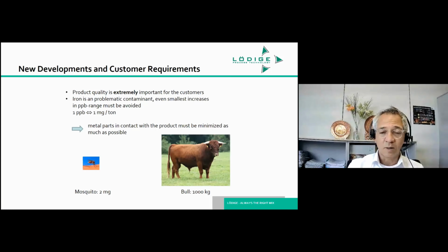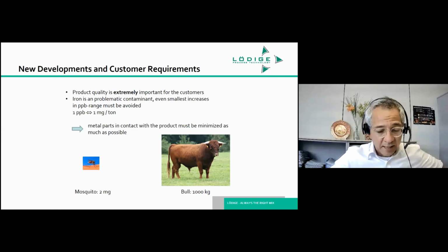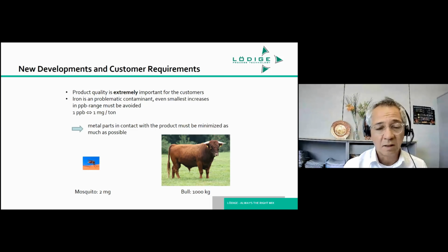Why the ceramic linings? Why the coating of all product contact parts? Well, the idea that foreign material gets into the mix to contaminate it is a very big headache for most battery producers. And so the idea is to avoid metal contamination as much as possible. And it goes to the extreme that the contamination has to be avoided in parts per billion. So we're not talking about parts per million, but parts per billion. And this means 1 milligram per ton of material of additional exterior contamination has to be avoided.